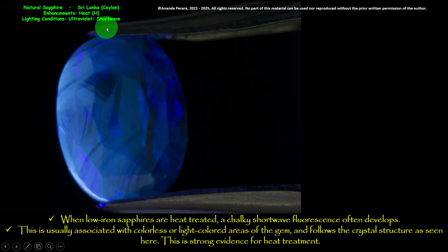What is this? Lighting condition here is ultraviolet short wave. This is also a heated stone. Then what happens here? When low iron sapphires are heat treated, inside this sapphire, iron is very low. So when low iron sapphires are heat treated, a chalky short wave fluorescence often develops under UV light.